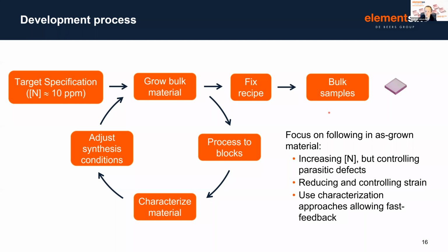So really in this study, what we focused on is 3 main properties and 3 main areas: increasing the nitrogen concentration, but whilst controlling the parasitic defects that I've been discussing. Obviously, crucially, reducing and controlling strain in these very high nitrogen concentration materials. And then, as I've remarked, really using characterization approaches that allow fast feedback of this process.